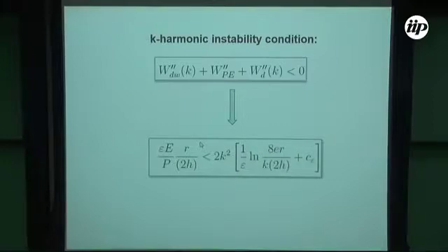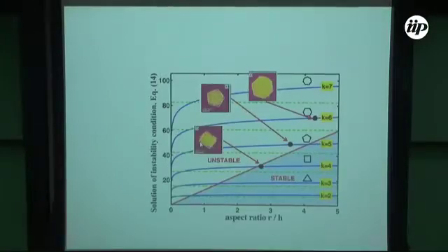I will show you the result. We were looking for the second variation with respect to harmonics with number k, and at which conditions the harmonic with number k becomes unstable. So this is the result of the instability. For different harmonics and different aspect ratios, we have a stable region and a region where the harmonics become unstable. This result was presented to experimentalists, and what is important is that harmonic number 6 has nothing particular in this story. Depending on the aspect ratio, we can have different types of instabilities.